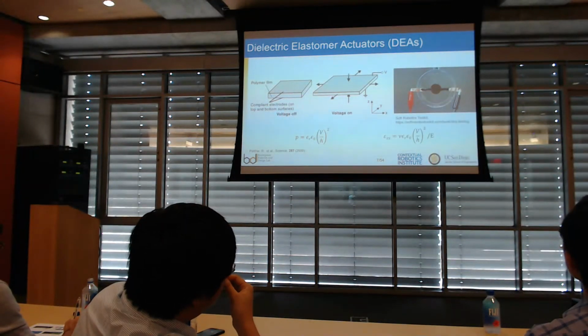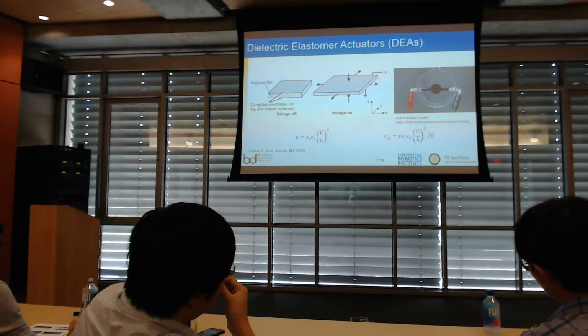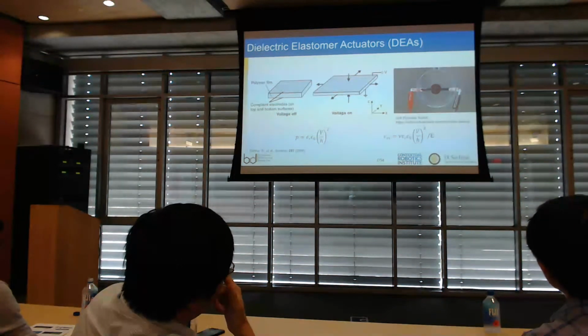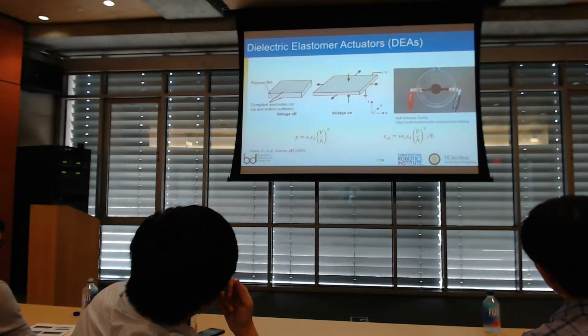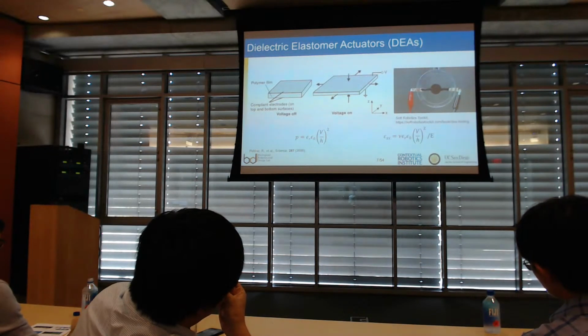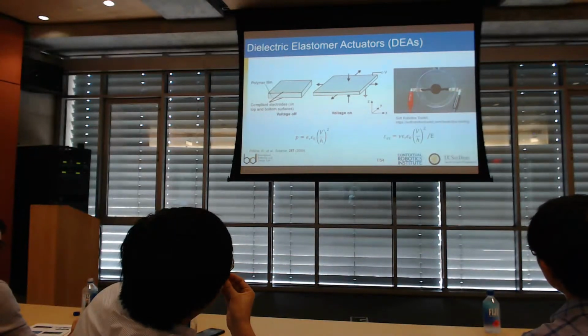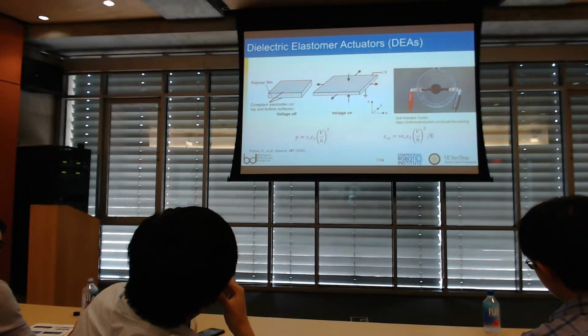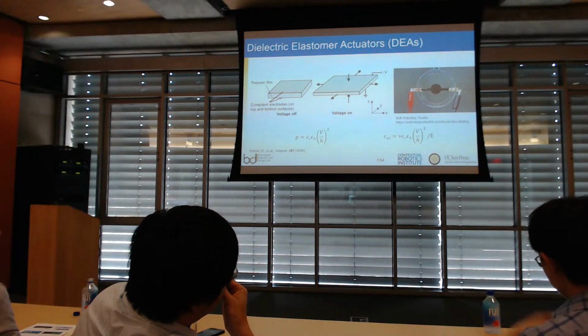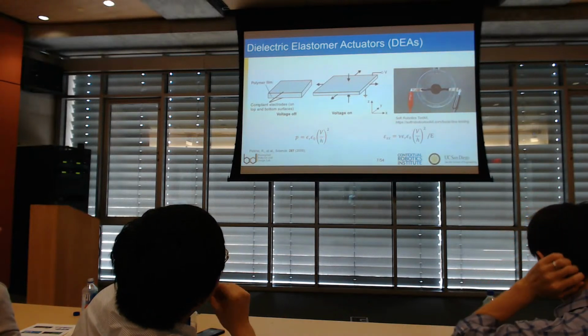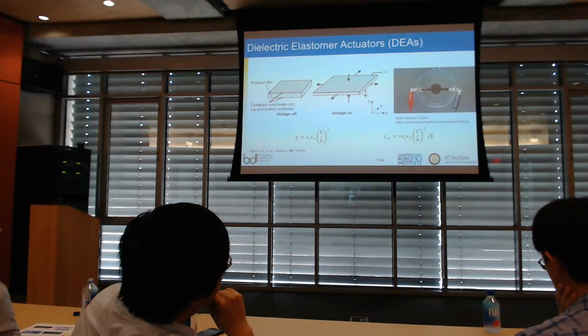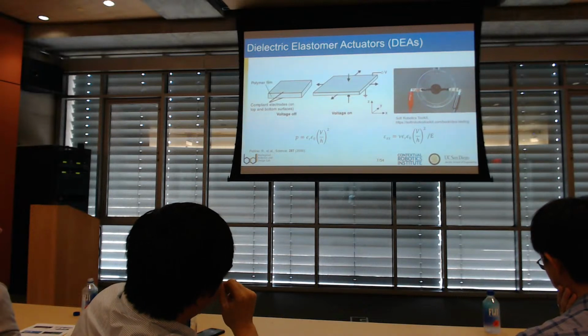So what this shows is that if we want to get large pressures or large strains, we have a few different variables that we can work with. The first one is the permittivity of the material. So we can select a material that has a high permittivity. So the materials that we're working with are anywhere from 2 to 4.7. The voltage that we apply. So you'll also see that the voltage and the thickness are squared. So there's a higher dependence on the voltage and the thickness of the material than there is on the permittivity.